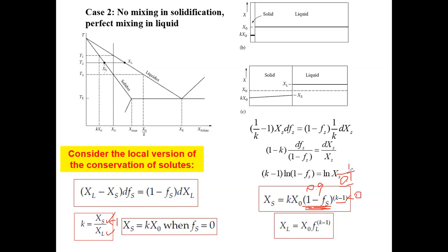If I have a small number for this whole thing, and I take the inverse to some power, this will be larger. So this mathematics is consistent with our analysis that this composition profile is a monotonic increasing function of fs. So those two parts check one another. Okay, so let's do the last check, where we'll see some surprise.